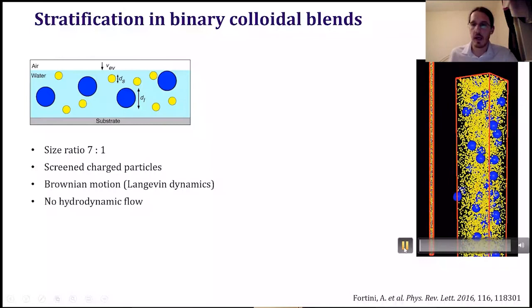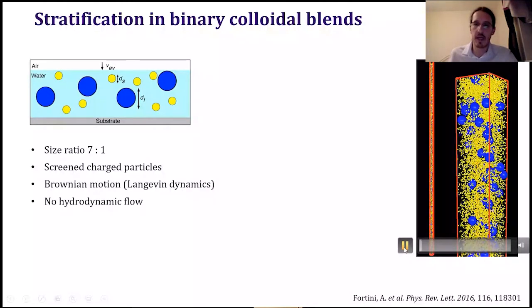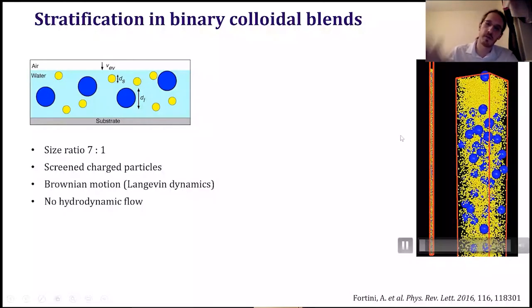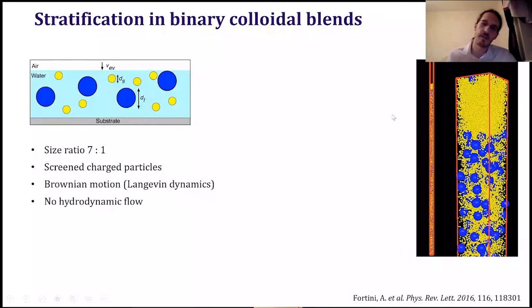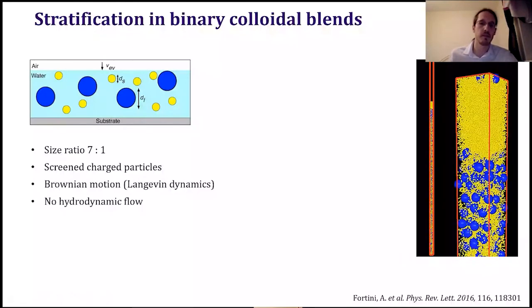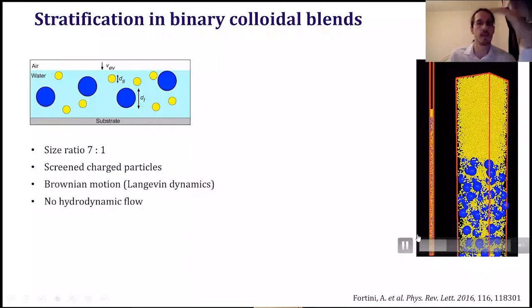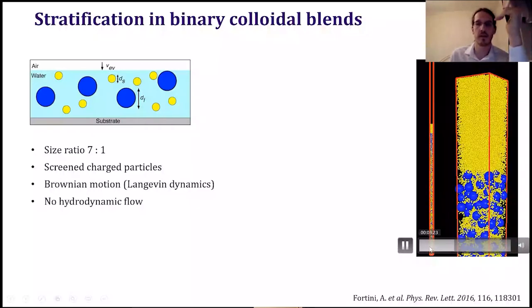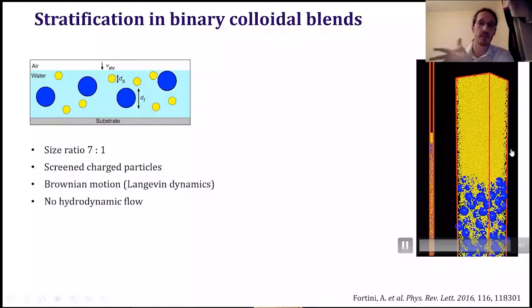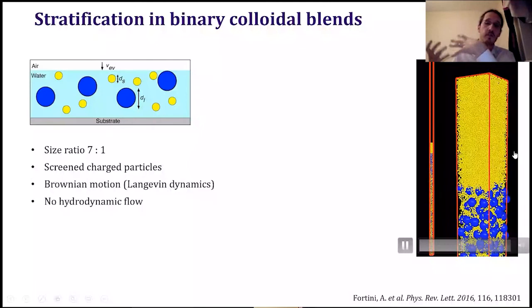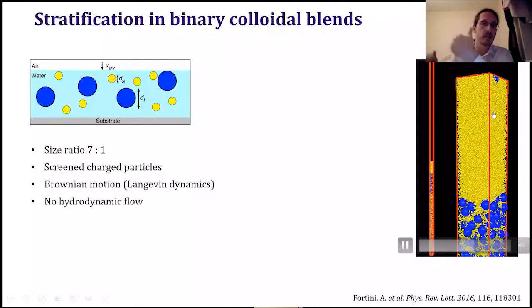Thank you. So you can see from the very beginning, you start with a homogeneous distribution of small and large particles. But from the very beginning, you see that the small particles, which are the yellow ones, start to accumulate at the top. So this is the air-water interface. And you can see there is a tendency for the small particles to accumulate at the top and form a layer there, and that stays there. So we have a system that spontaneously self-stratifies. It forms two layers without us needing to deposit one and then the other.